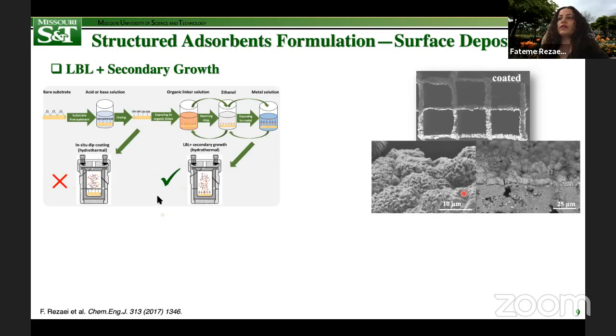On the other hand, among various coating methods, layer by layer or LBL combined with the secondary growth step was found to be successful in MOF crystal nucleation and growth. And under optimum conditions, a very uniform and homogeneous MOF layer was formed on the cordierite surface as shown by these SEM images.